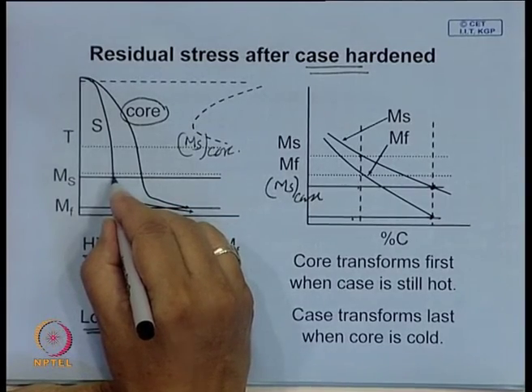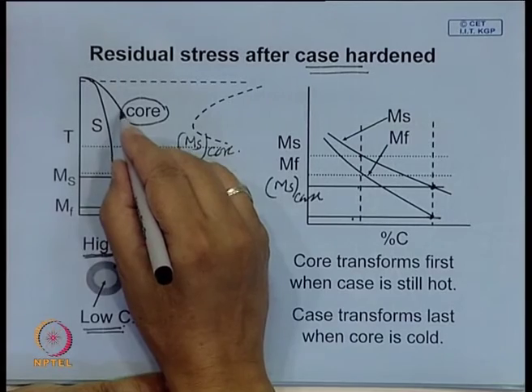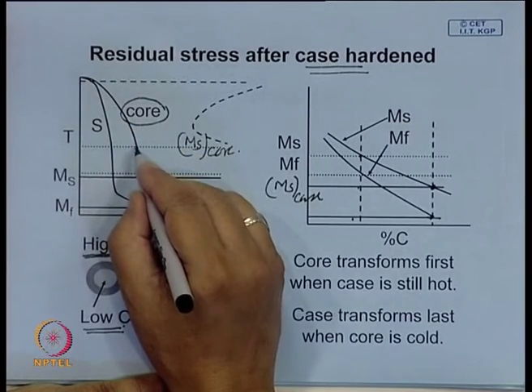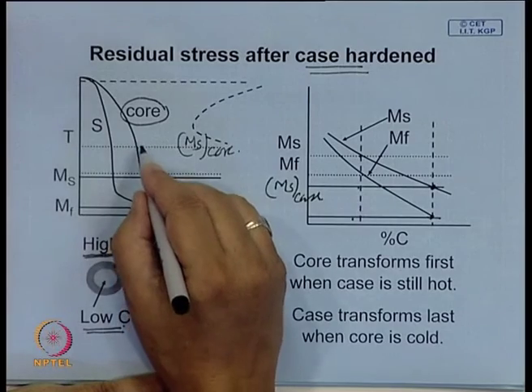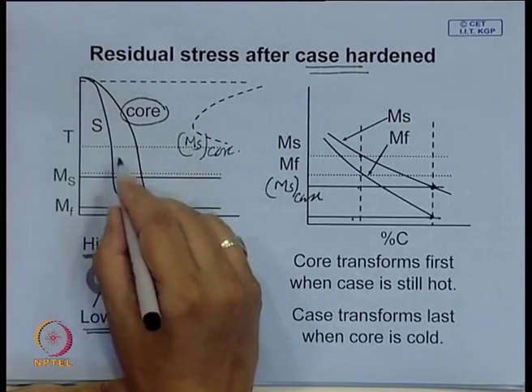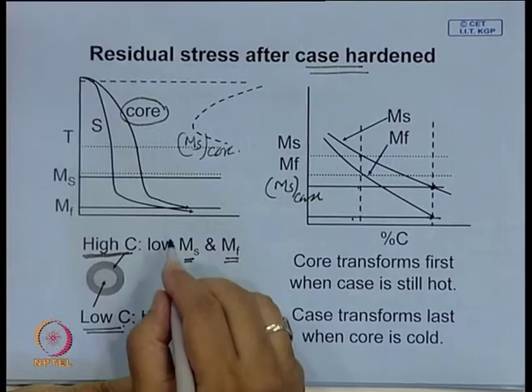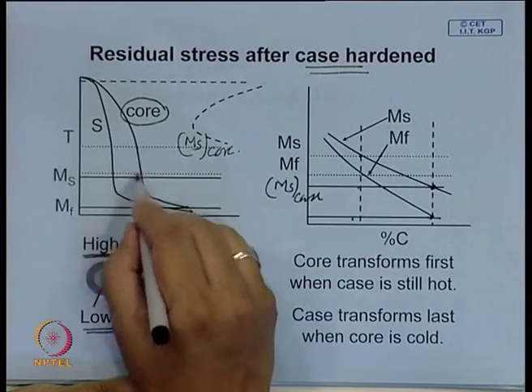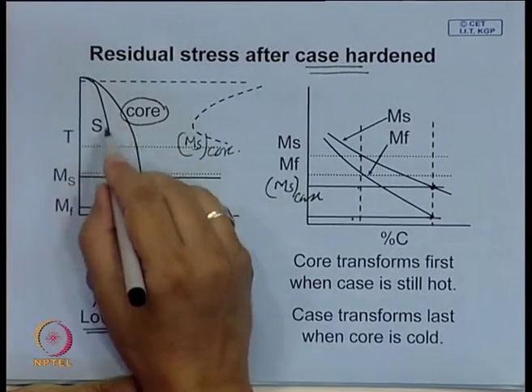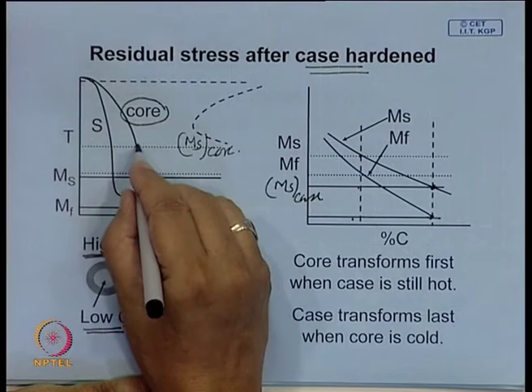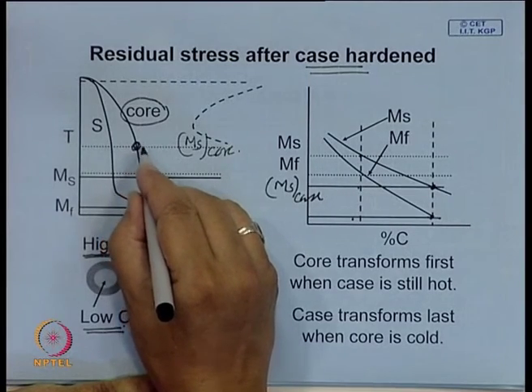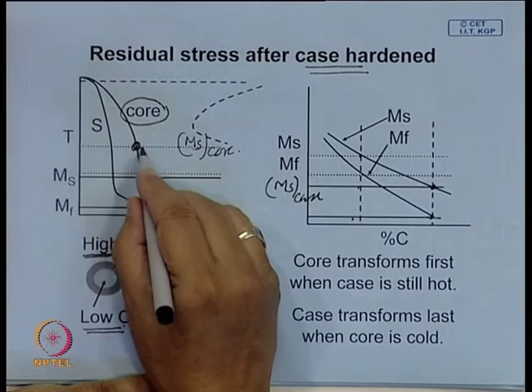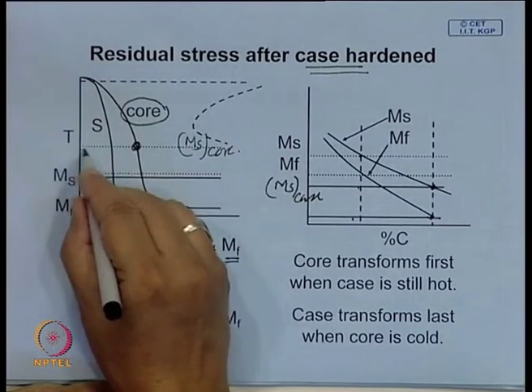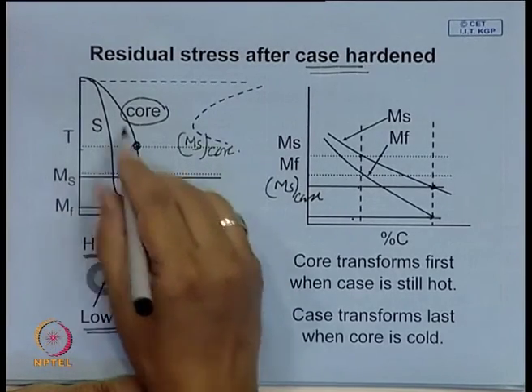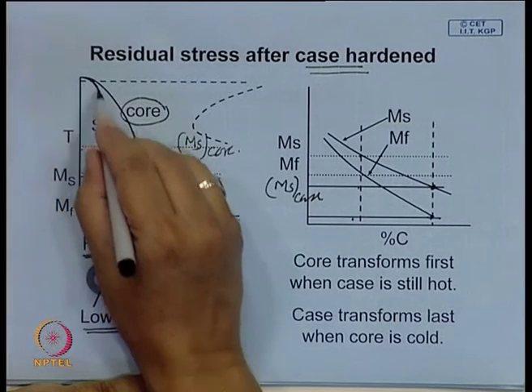transformation begins in the case, although the case temperature is lower at any instant. So here you will find this temperature. Therefore, what happens at any instant, this is not to scale, it is possible by controlling the cooling rate to allow the transformation to begin first here, in the case, before this starts. So this line should be, I think, a little to this side.